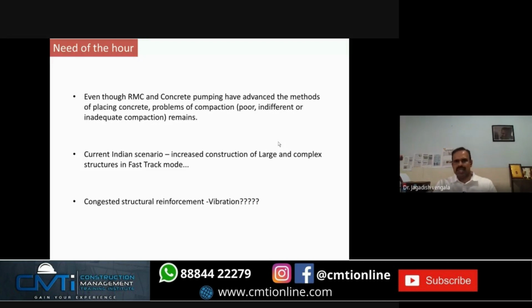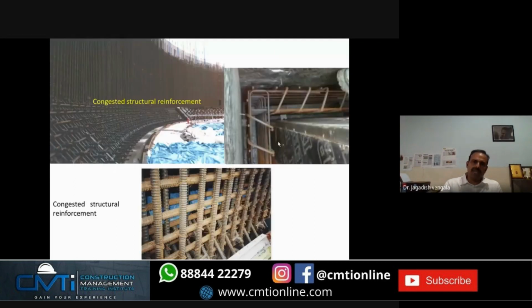As I mentioned already, RMC and concrete pumping have advanced the methods of placing concrete, but problems of compaction are still remaining at most of the sites. And in the current Indian scenario, you see a lot of construction of large complex structures, particularly in fast track mode. So with congested structural reinforcement, vibration is a problem. Take these pictures. Can you insert the concrete vibrator and vibrate the concrete? Why do you have to vibrate the concrete? When you place the concrete, there are small air pockets. When you vibrate it, all the air pockets come out and then you get a dense concrete. That is the purpose or significance of vibrating the concrete.